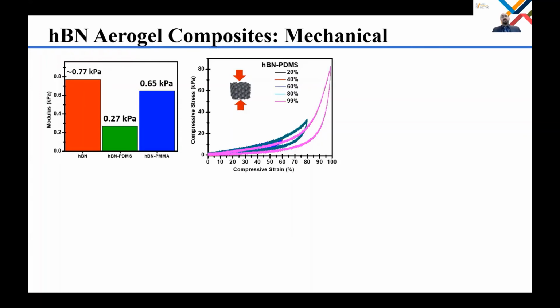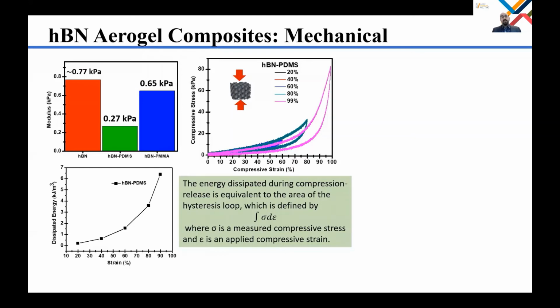The maximum stress for hBN-PDMS aerogel is 82.4 kilopascal at 99% strain, and this indicates that this structure can tolerate a large deformation. And hBN-PDMS composite aerogel shows an exceptional hysteresis loop during compressive loading and unloading cycles, and this indicates that hBN polymer composite aerogel has significant mechanical damping properties. To quantify the damping capability of the composite aerogel, here we calculated the estimated dissipated energy. This dissipated energy corresponds to the area of the hysteresis loop during compressive loading and unloading cycles.